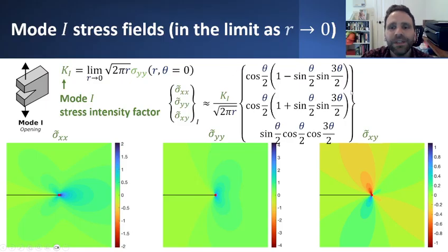And really, this solution only applies in the limit as you get closer and closer to the crack tip. So in the limit as the radial distance r from the crack tip goes to zero, this particular solution field for the stresses, the in-plane stresses in particular, becomes valid. And it'll look the same, again, regardless of the loading scenario, regardless of the geometry of the plate. So in this particular case, you'll notice that sigma xx, there's definitely some large infinite stresses. Even in this stress in the horizontal direction, it dies off as you move further away from the crack tip in different directions.